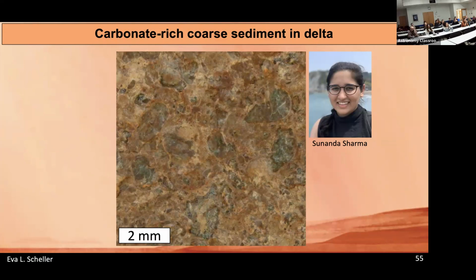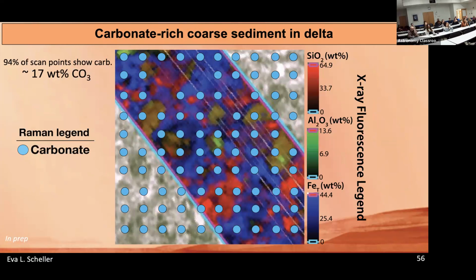Now, let's look at the chemical results. So here is one of these compilation products that we're going to produce where we can see the Raman spectra in compilation with the X-ray fluorescence results. And you can see we observe a lot of carbonate in the Raman spectra. Again, each of these blue points is a spectrum like we saw before. And the iron in the X-ray fluorescence maps is largely following this iron carbonate that we observe. You can also see more silicate-rich areas. Those tend to be the silicate grains that are present in this fluvial sandstone. But the really key observation was we had upwards of 28% carbonate in this fluvial sandstone that we did not necessarily anticipate that we were going to have.